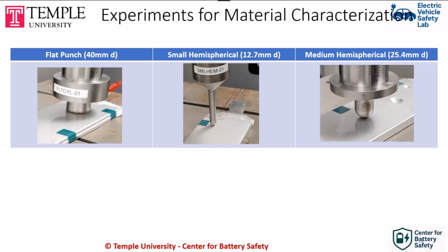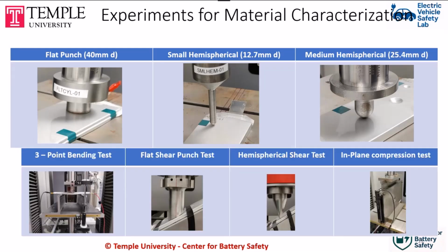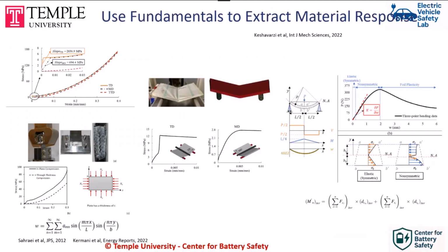So what we need to do is we need to now calibrate the material property with that understanding, but from cell level testing. So we apply different type of punch loading, flat punch, hemispherical punch loading, and global loading, bending, in-plane loading to the cells. And then we try to extract the material properties from cell level testing instead of having all of the properties of all of the components and get the properties of the homogenized material.